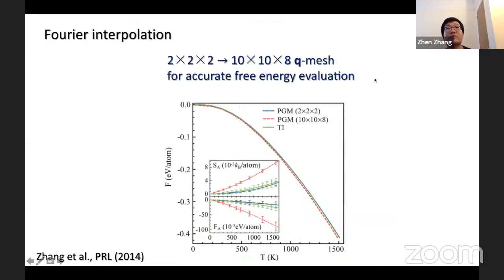Then vibrational entropy and the free energy were calculated with a 2x2x2 Q mesh directly sampled by the phonon quasiparticles. Thermodynamic integration from ab initio MD with 2x2x2 supercells was also conducted for comparison. Results by these two methods compare well with each other, meaning that the present phonon quasiparticle approach well captures the anharmonic contributions to the vibrational entropy and free energy.